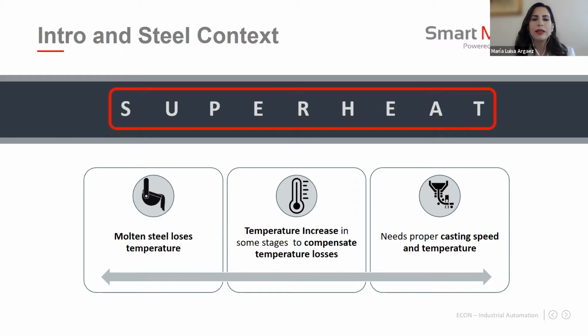It is well known that the superheat in the steel is the difference between the steel temperature in the tundish and the liquidus temperature. Therefore, ensuring compliance with the superheat in the tundish zone within the range of 15 to 30 Celsius degrees is one of the key objectives to maintain a high quality of the final product.